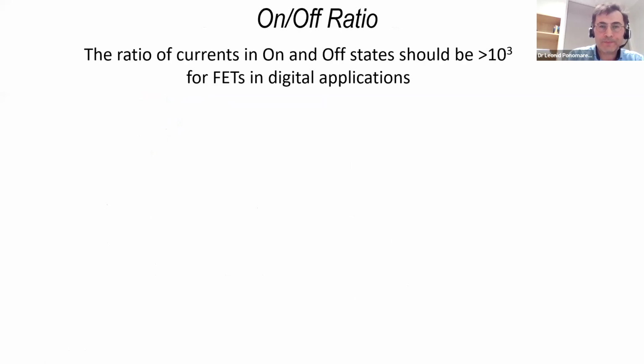Okay, so now, of course, nothing is ideal in this world. So the current in off state cannot be infinitely small. It cannot be zero. So then the important parameter that researchers and engineers use when they are making a transistor and judge if the transistor is good is the so-called on-off ratio. So it's a ratio between currents in on and off states. And in order to be suitable for digital applications, this ratio should be at least 3 orders of magnitude, at least 1000.